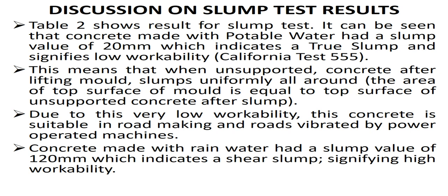This means that when unsupported, concrete after lifting mold slumps uniformly all around. The area of top surface of mold is equal to top surface of unsupported concrete after slump. Due to this very low workability, this concrete is suitable in road making and roads vibrated by power-operated machines. Concrete made with rainwater had a slump value of 120 mm, which indicates a shear slump, signifying high workability.